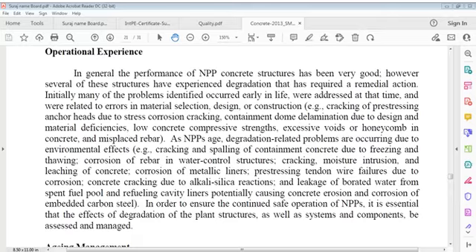Initially, many problems identified occurred early in life, were addressed at that time, and were related to errors in material selection, design or construction: cracking of pre-stressing anchor heads due to stress corrosion cracking, containment dome delamination due to design and material deficiencies, low concrete compressive strength, excessive voids or honeycomb in concrete, and misplaced rebars.